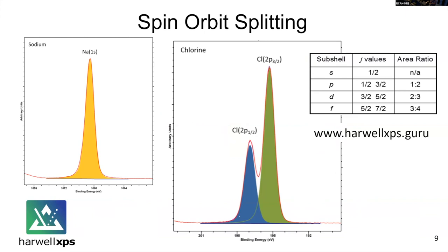For d orbitals, it's 2 plus or minus a half, and you get this characteristic double peak. The separation between the peaks depends upon the atomic number and the orbital that's concerned, but it's characteristic. And the ratio between the areas of these peaks is also absolutely known. So these are very characteristic peaks you will see in any